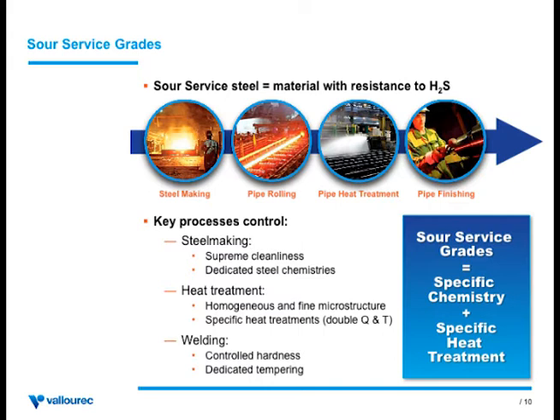So we have some specific steelmaking processes that are much longer, require more time, more complex than for other types of grades. There are also some chemistries, always proprietary, that are being used. And heat treatments, of course, the quenching and tempering process for both the tool joint, the weld, the pipe body is very important and will not be the same as any standard drill pipe. In some cases, there could actually be several quenching and tempering processes made on some part of the product to basically reach the performance we are looking for and eventually pass the NACE test.